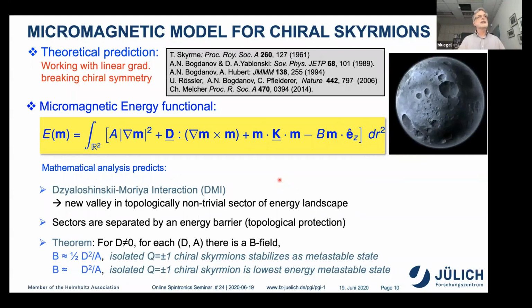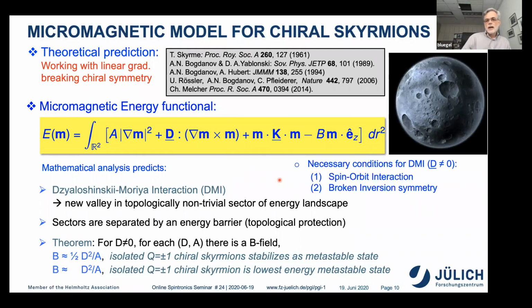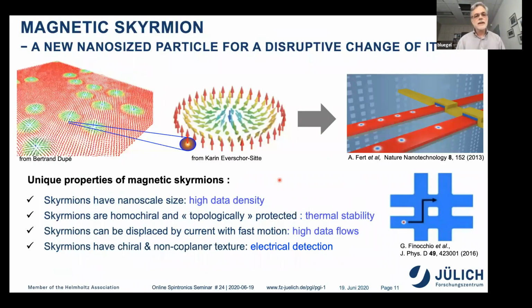So basically what they have proven is, if the parameter space is correct, among all non-trivial topologies, the skyrmion with the topological charge -1 is the one with the lowest energy. Since this skyrmion behaves like a particle of finite size and has a certain stability, it is of course very attractive as a new particle for spintronics, to make a disruptive change of information technology. And the unique properties of the magnetic skyrmions relate to high data density, to thermal stability, to high data flows due to fast motion, and to electrical detection, for example, due to non-collinear spin textures.